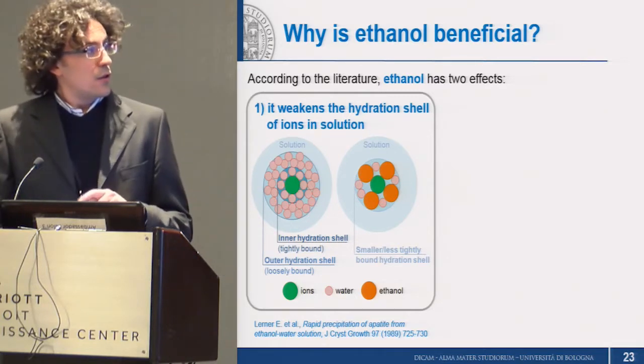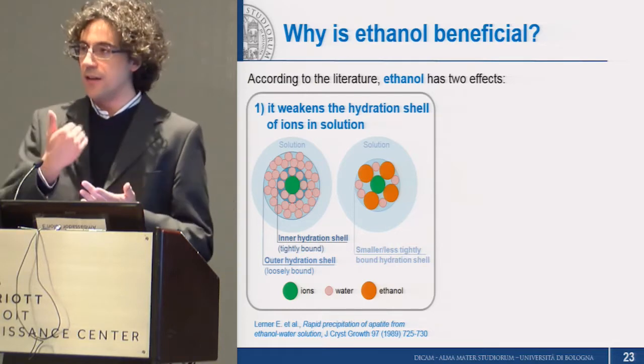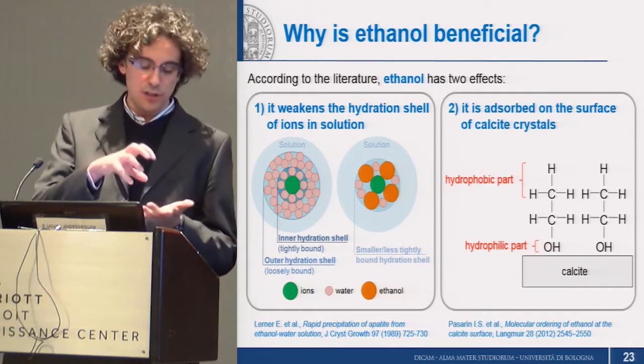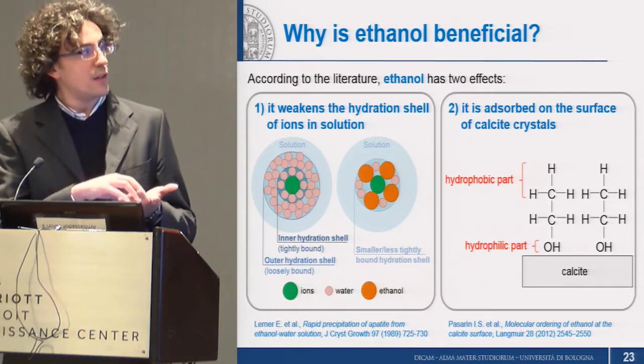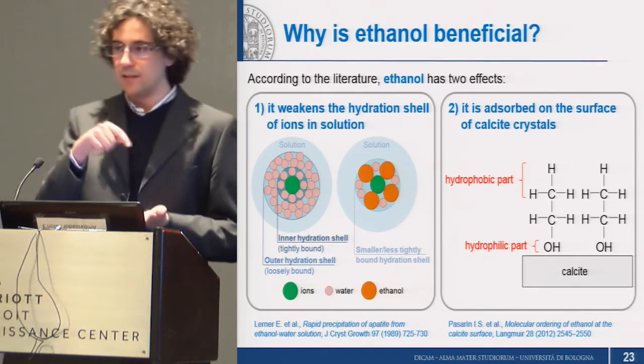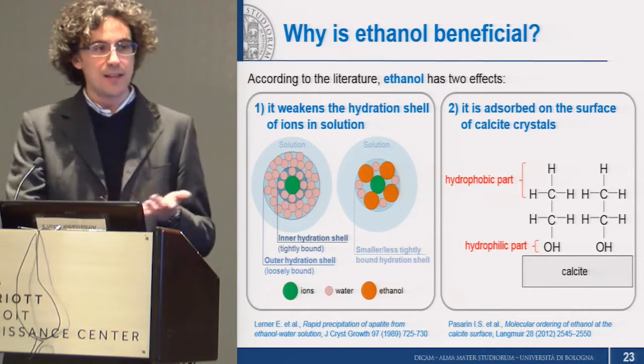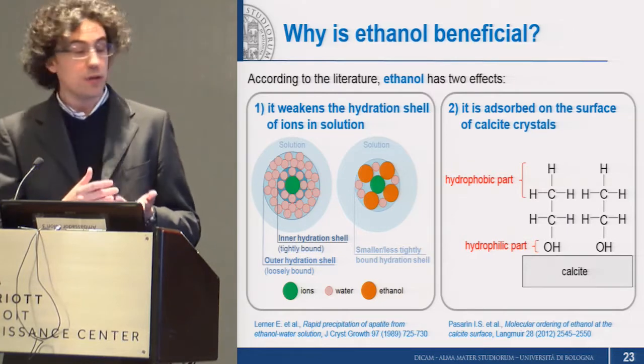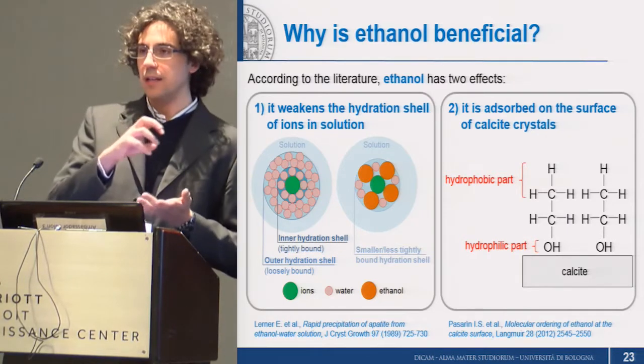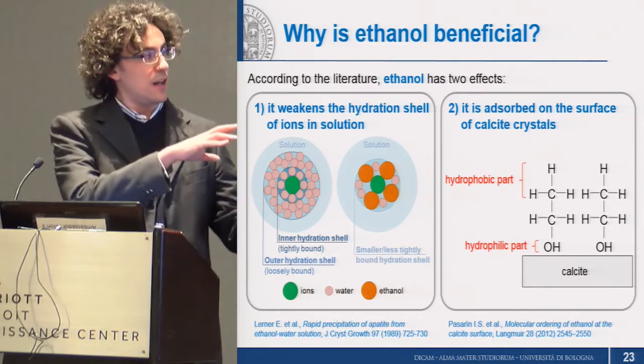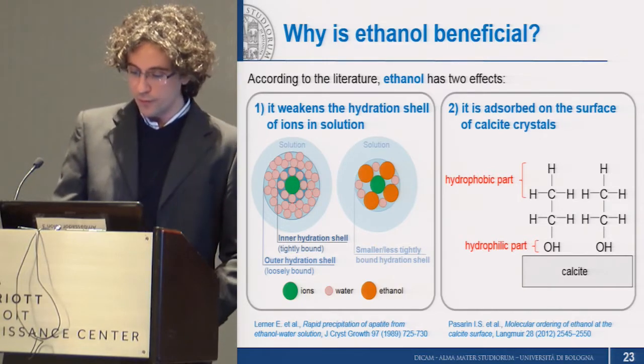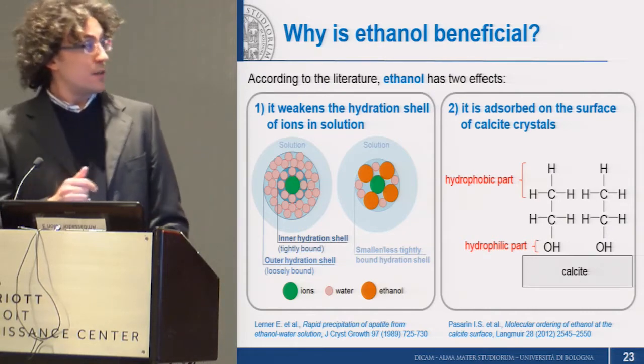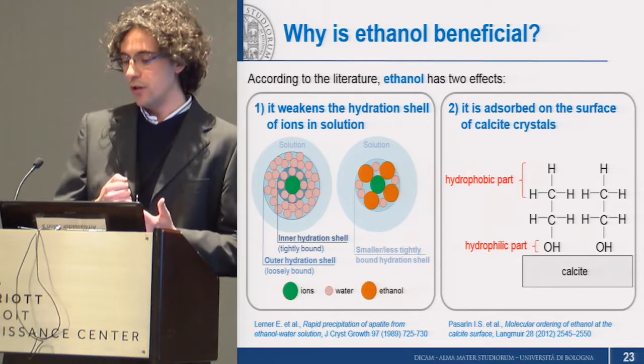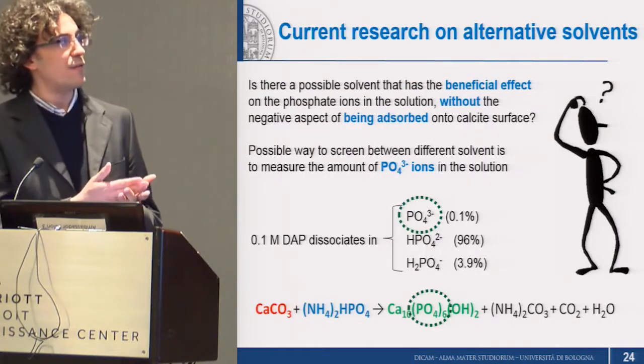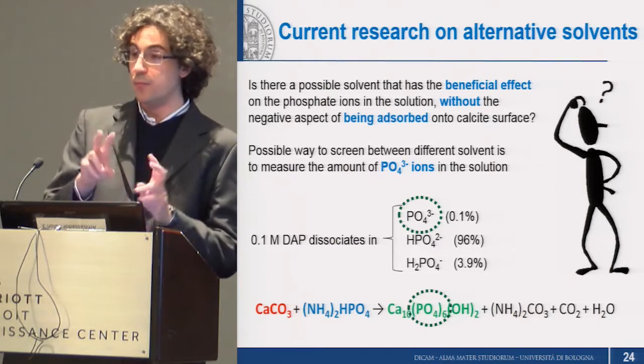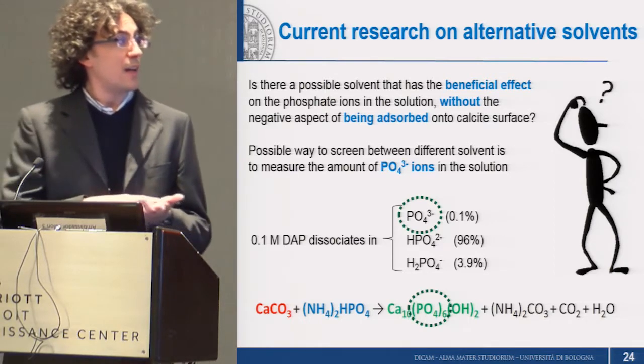However, ethanol is also reported to have another effect that in our case might be counterproductive, which is being adsorbed onto the calcite surface, which means that the ethanol molecules orient themselves with the hydrophilic part towards calcite and the hydrophobic part towards the bulk solution. And this may be a problem because this may limit the speed and the reactivity between the substrate and the solution. This is why we have recently started investigating the possible use of alternative solvents that have the positive effect in the solution, let's say, without having the problem, in our case, of being adsorbed onto the calcite surface.